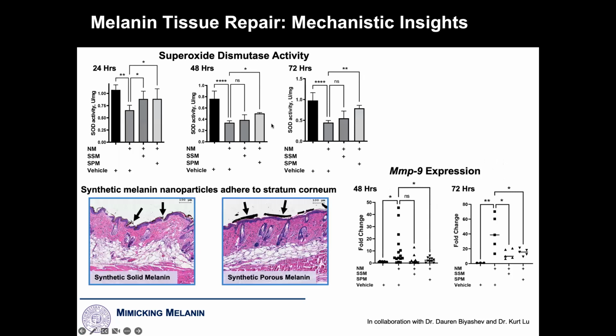And so we see a reduction in superoxide dismutase activity. What is this? This is an enzyme that you naturally have in place to quench radicals. They get overwhelmed and damaged by this nitrogen mustard treatment. And we can recover its activity by essentially helping it to scavenge radicals. And by the way, this is purely from melanin being stuck to the surface. So this is a topical treatment, right? That's having a downstream immune effect, a downstream initial enzymatic recovery, and then ultimately an effect on the immune system that recovers.